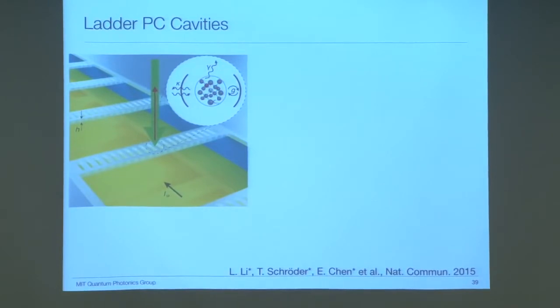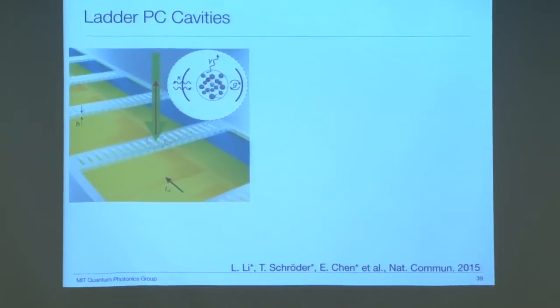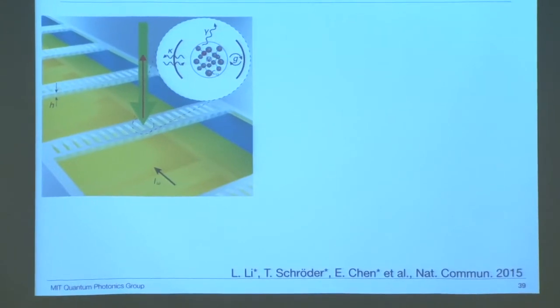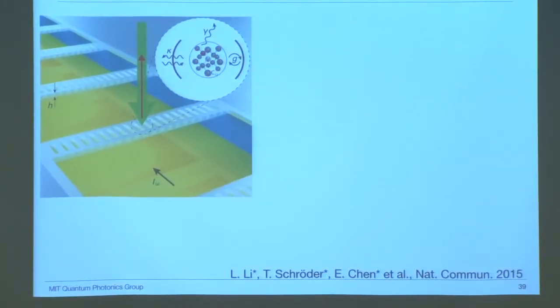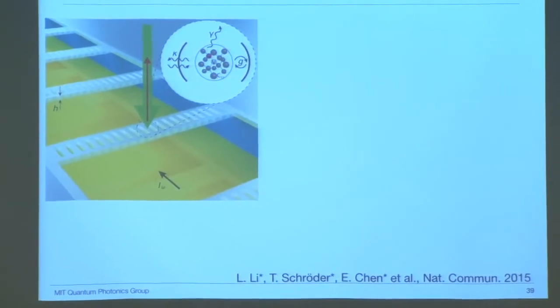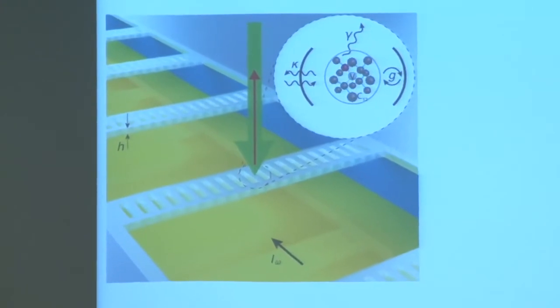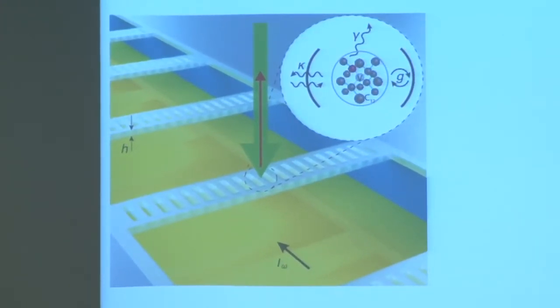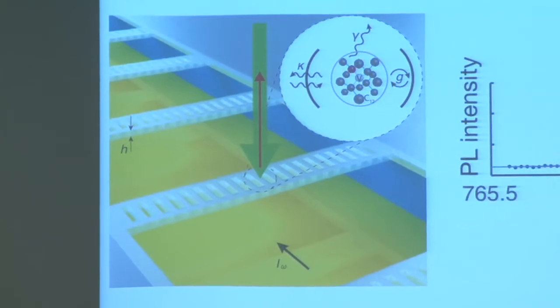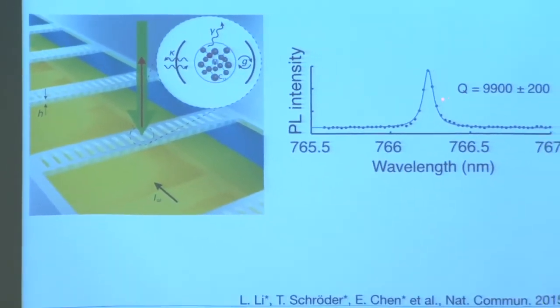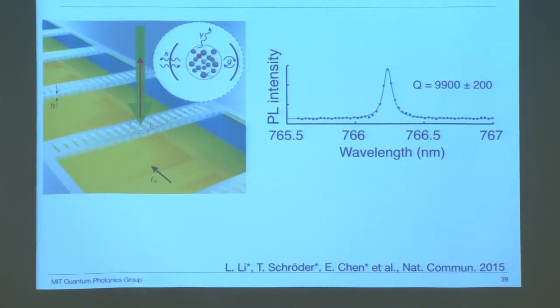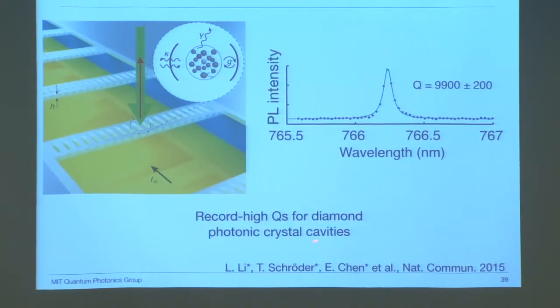We tested these cavities using a scanning confocal microscope with a 532 nanometer excitation laser, and the collection is using the same objective lens. The broad phonon sideband of the NV provides an internal light source for our cavity measurement, which allows us to simply record the photoluminescence to find the cavity resonance. And this is one of the fundamental modes that we found for our photonic crystal cavity. It's approaching 10,000. It happens to be a record high quality factor for a diamond photonic crystal cavity fabricated for this spectral range.